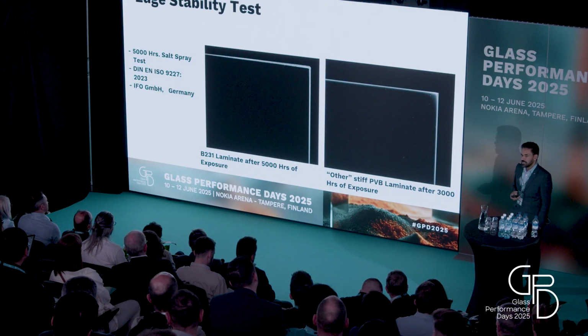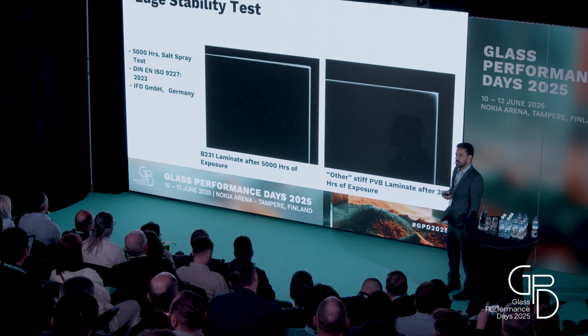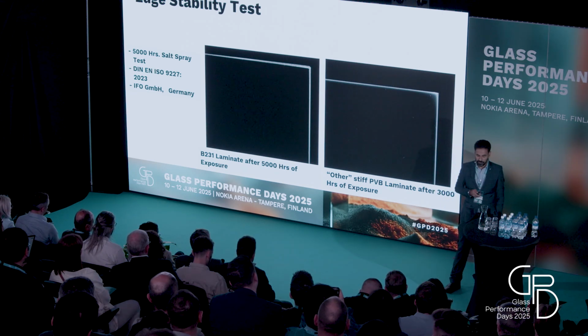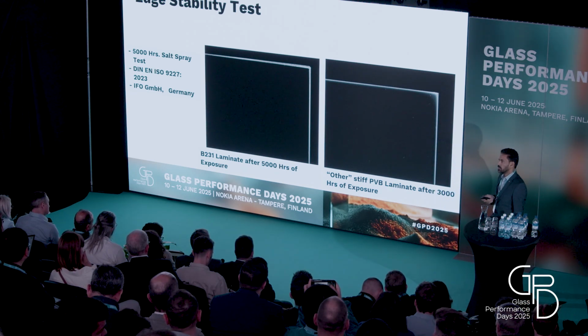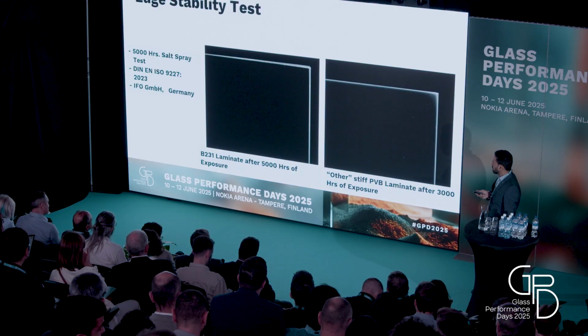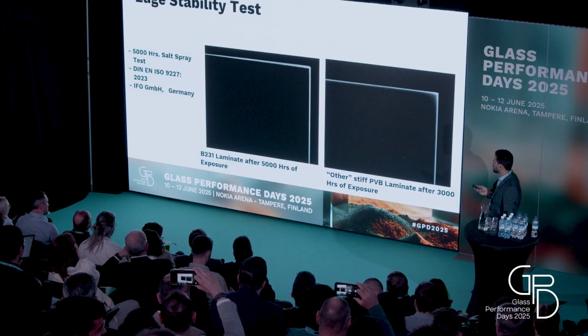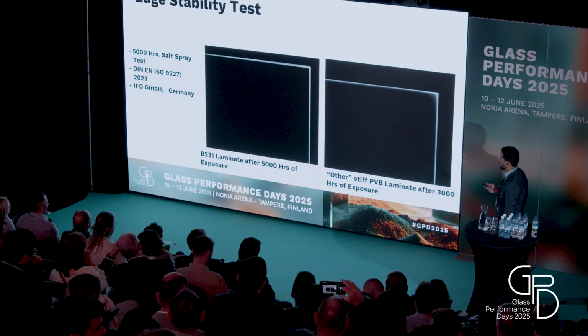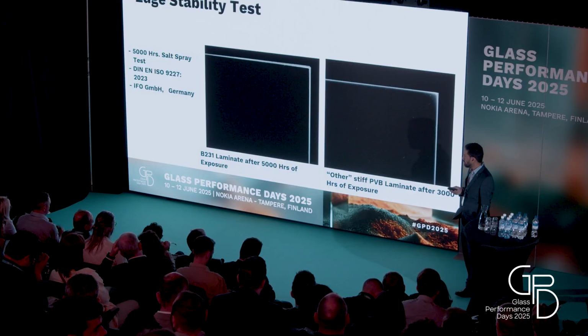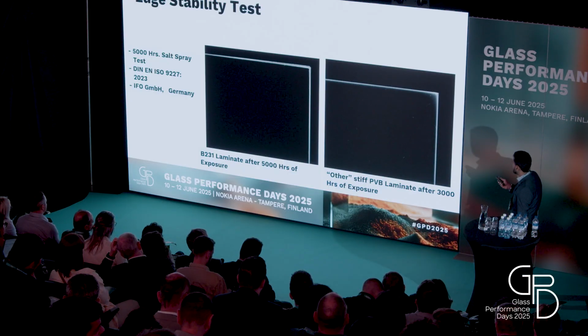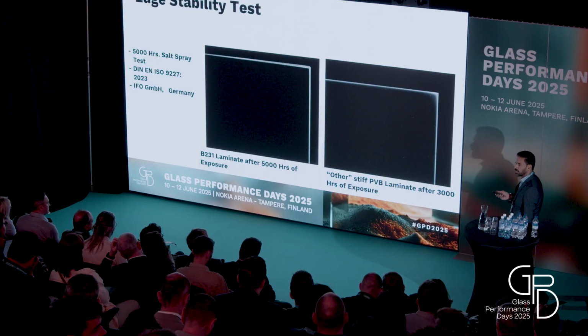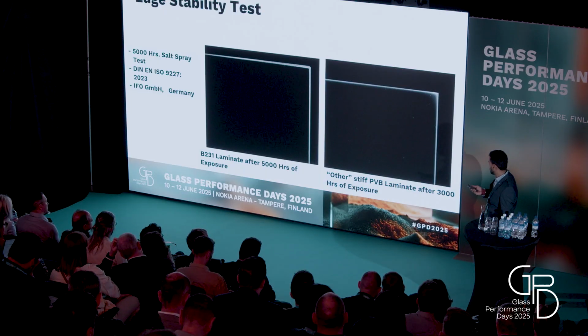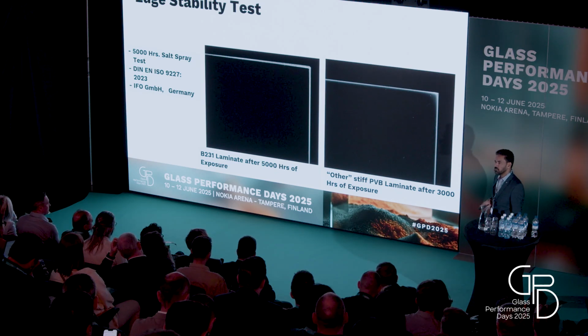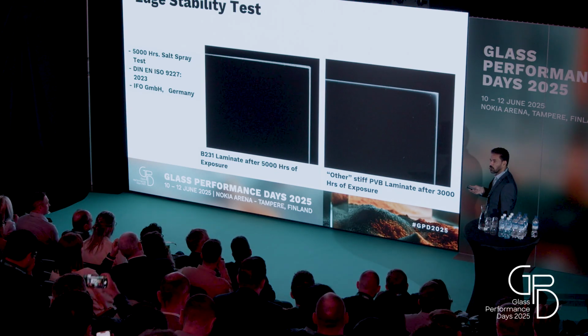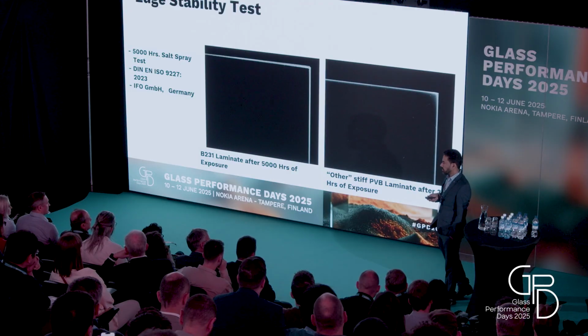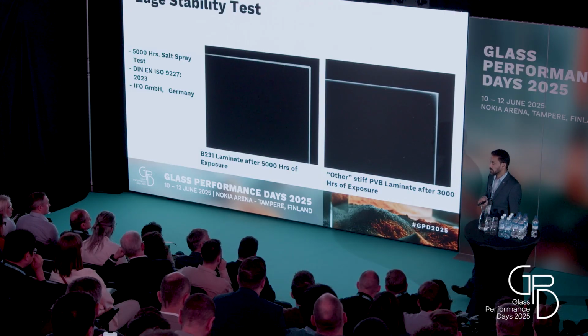Then we were talking about the glass balustrades. Quite often these applications have their edges exposed to the environment, which means edge stability is very important to be checked. So we tested the improved stiff PVB with the existing stiff PVB, and we found that it has a much better edge stability, because here you can see there is a cloudiness that was observed at the corner of the glass laminate after just 3,000 hours. Whereas the improved stiff PVB showed no cloudiness at the edge even after 5,000 hours of exposure to the salty environment in the test.